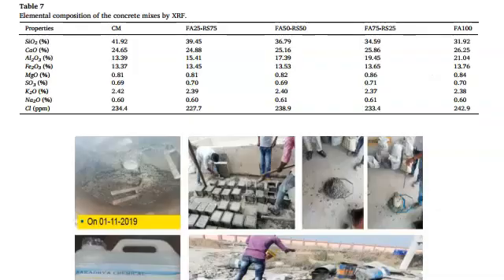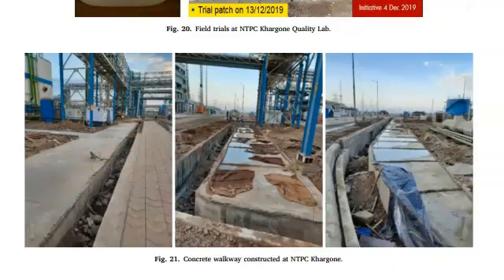But further literature review also revealed some interesting things, that if you're adding certain chemical additives, for example, I'll name one, others are also listed in my publication as well. The one I'm talking about is polyethylene glycol, PEG. PEG is actually a very commonly occurring material. It is also being used in food processing and drug manufacturing industries. But if you are using heavy molecular weight PEGs, that is PEGs with molecular weights greater than 6,000, they actually increase the curing potential of the component.